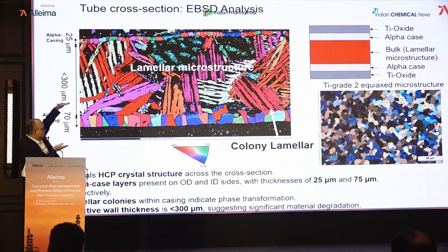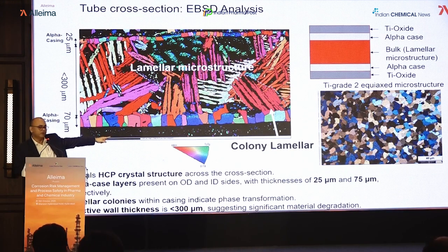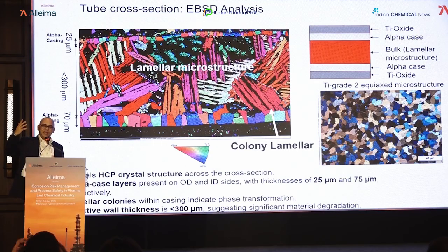These two case kind of features, the layer kind of feature that you are seeing from both sides, are basically what we call alpha case. And in the center, you have a lamellar kind of morphology. Ideally, you should have an equiaxed kind of microstructure, but what you are seeing is lamellar. I have worked in titanium a lot, so I know. This is generally when it is exposed to high temperature and then cooled, you get this kind of microstructure.